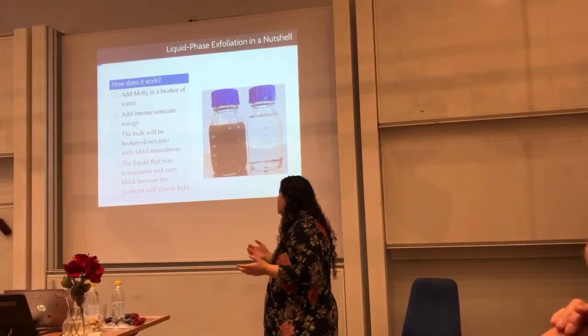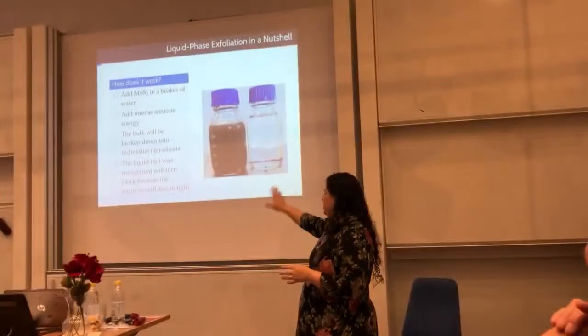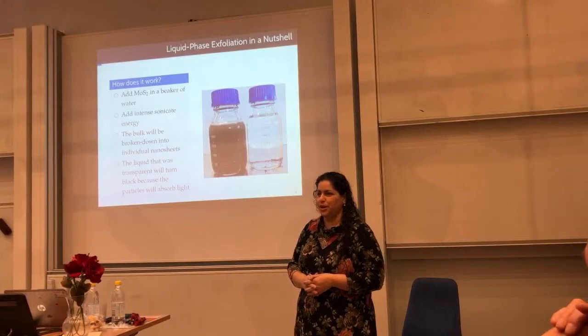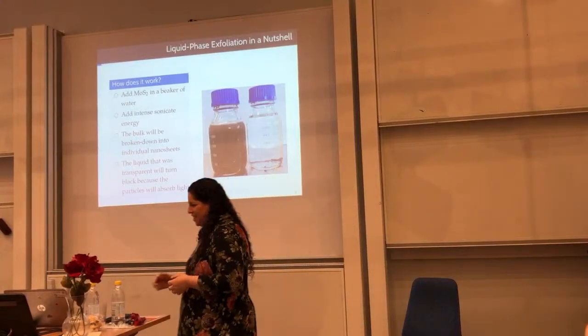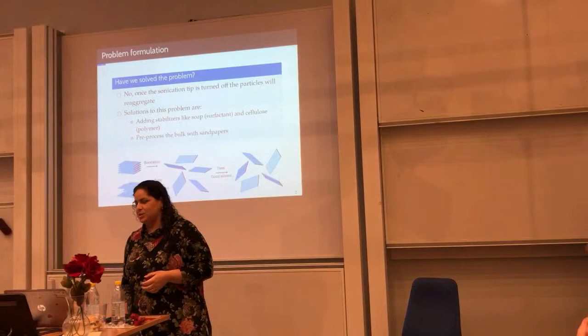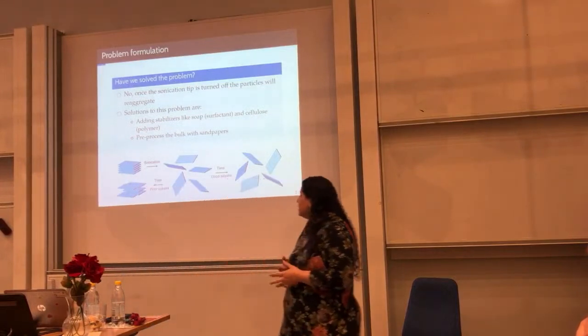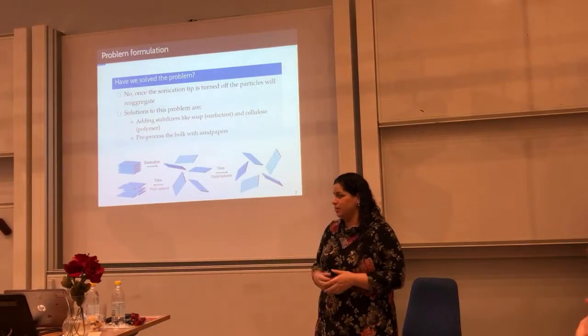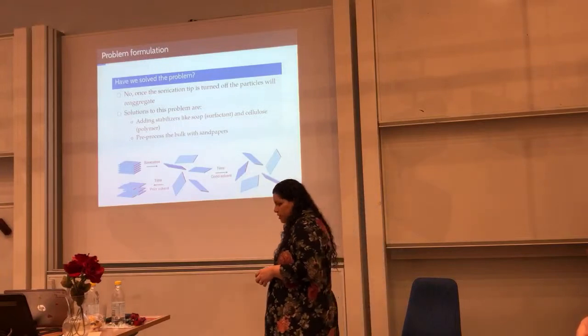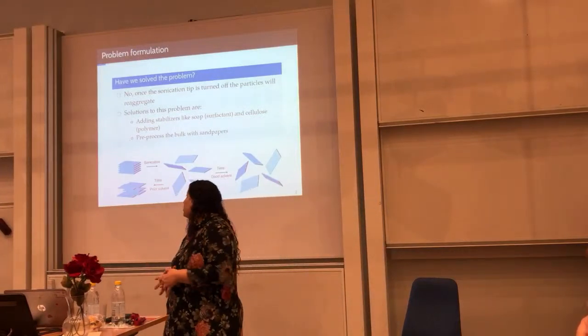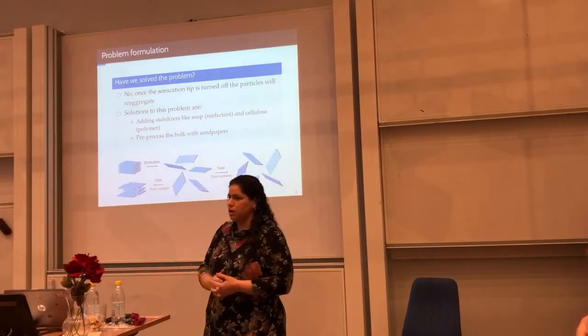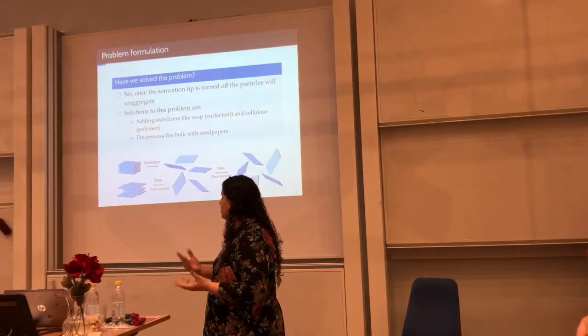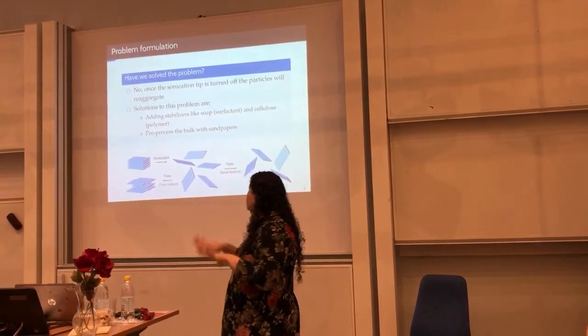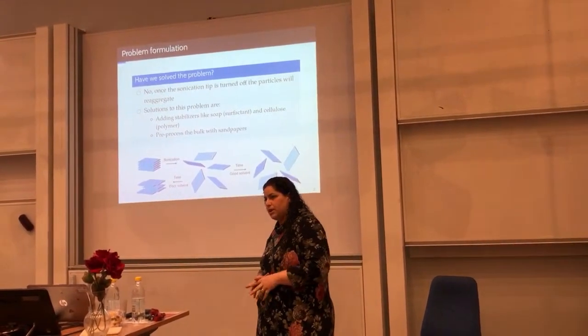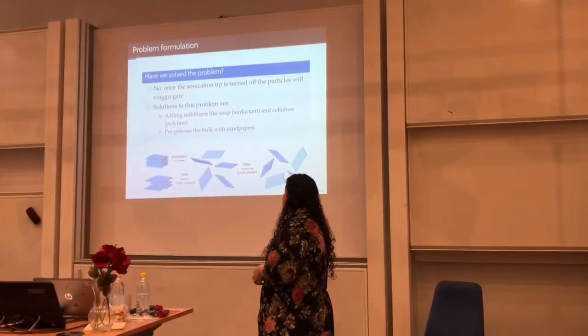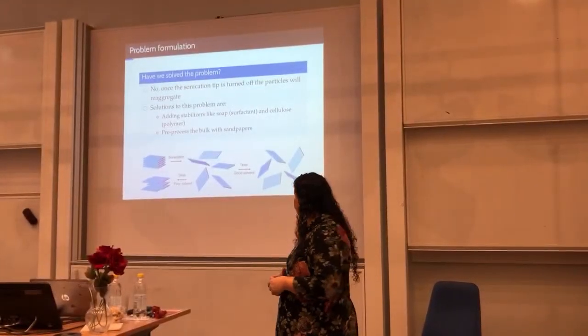If everything was easy as we wish it to be, that would be all. We wouldn't need to do more work, but it's not like this, right? Thermodynamics says that this system wouldn't work because these layered materials don't have a matching surface energy with the water. So once you stop providing this sonication energy or the shear exfoliation energy, these particles will aggregate and sediment, so they will stack back together if it's in water.